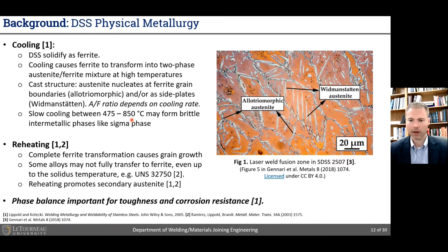When thinking about reheating a duplex microstructure, in some alloys we can get complete transformation to ferrite above the ferrite solvus temperature. However, in some alloys they may not be able to fully transform to ferrite even up to the solidus temperature, as has been reported by Ramirez et al., for example, in the 2507 type alloy. It's also known, as has been reported by Lippold and Kotecki, Ramirez et al., that reheating can promote secondary austenite formation, called secondary because it's forming under reheating.